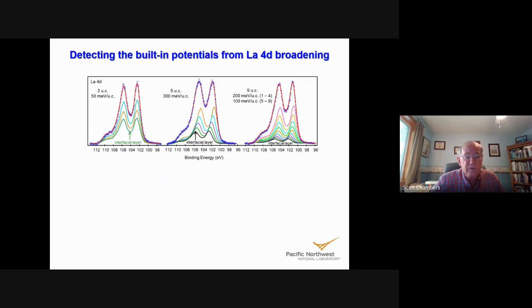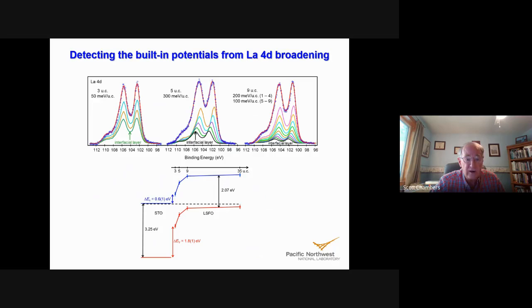And we can find out what that band bending is by doing what we had on the previous slide, 2 slides ago. Go ahead and take a flat band spectrum that we get for a reference sample that doesn't have any band bending, assign that to each of the layers, then vary the spacing, the energy between those layers, and try to fit the spectrum. And if we do that for the 3 different film thicknesses, which is shown here, then we can construct the entire band diagram for the whole thing.